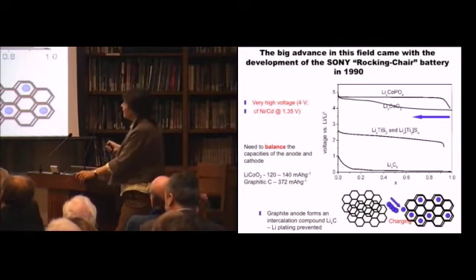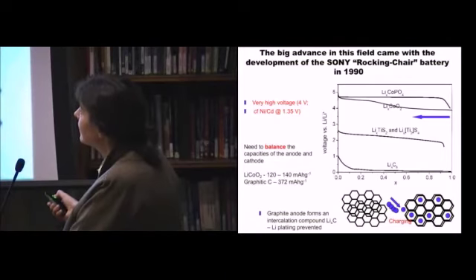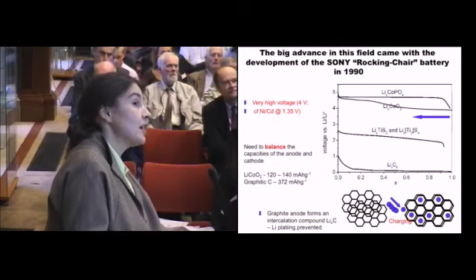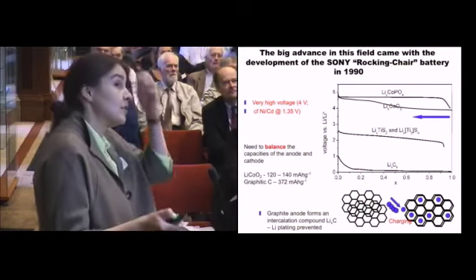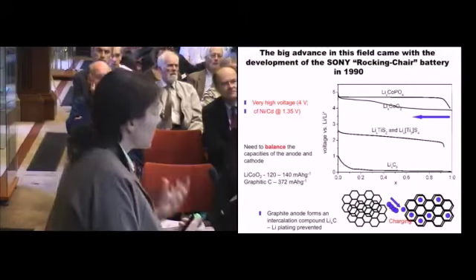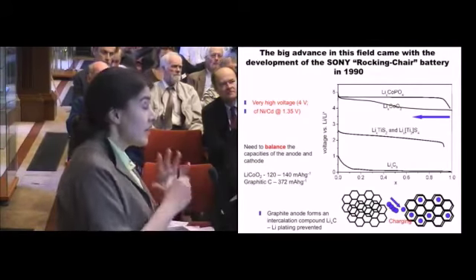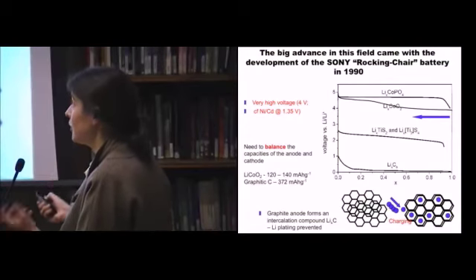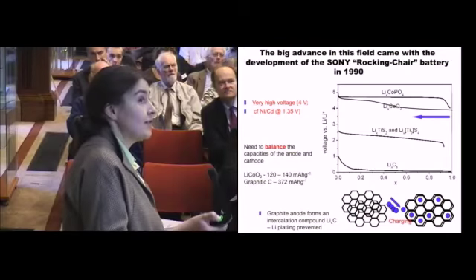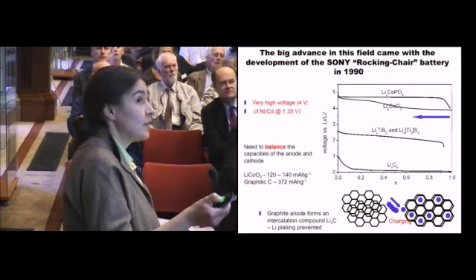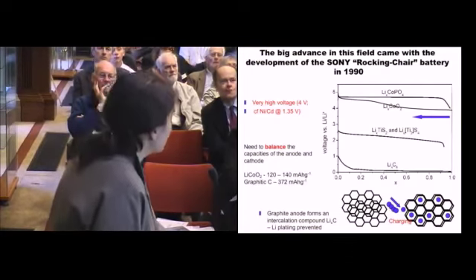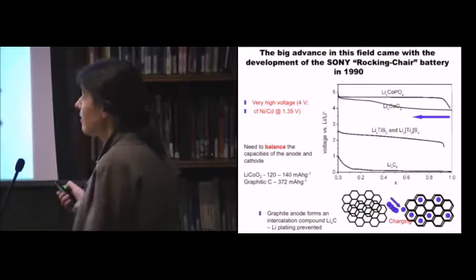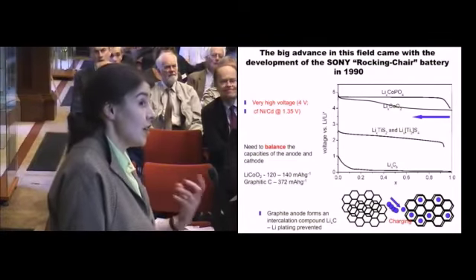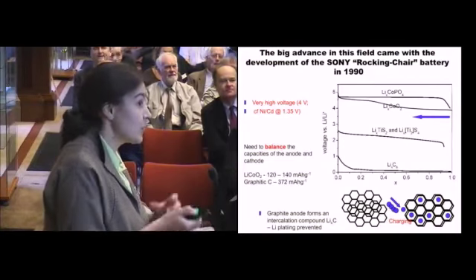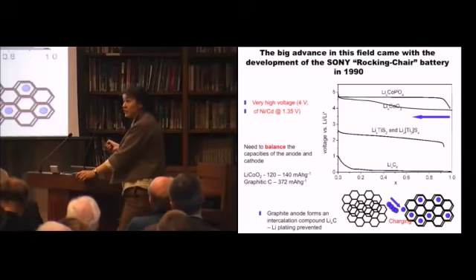So you gained this extra 2 volts from moving from lithium titanium sulfide chemistry to lithium cobalt oxide chemistry, and that comes from the replacement of sulfur with oxygen. Without going into all the details, it's important to realize that the chemistries, the local environments and the elements have a tremendous difference on the voltages that these batteries operate at. So here's lithium going into carbon, here's lithium in titanium sulfide, lithium in cobalt oxide, and then if you put lithium into a cobalt phosphate, you get an even higher voltage. And so as a chemist, what we can do now is to play with the different environments of the elements and of lithium in the compound and the different elements to try and tune the voltages of the materials and thus the energy density.